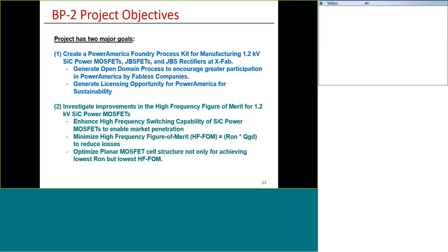So I've defined a high frequency figure of merit to allow us to do this optimization. It is the product of R-on, which is a measure of conduction loss, and QGD, the gate charge during the plateau, which is a measure of switching losses. So by taking the product of these two parameters, we get a product that is independent of the area of the device and is a measure of the technology and design.